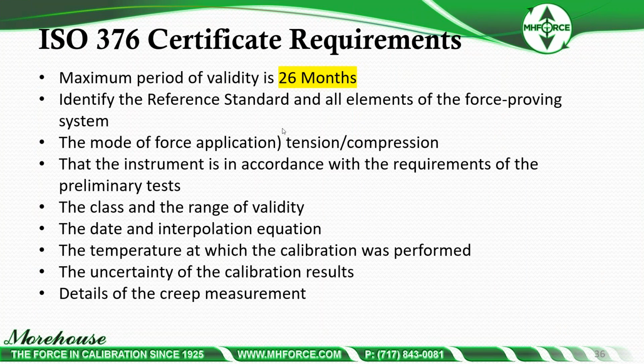I just showed you our typical certificate for ISO 376, the Morehouse certificate for ISO 376, but ISO 376 has additional requirements. Maximum period of validity is 26 months. Identify the reference standard in all elements of the force proving system. That's cables and everything else, top locks if they're included with serial numbers, everything. The mode of force application, tension, compression, that the instrument is in accordance with the requirements of preliminary test, the class and range of validity, the date and interpolation equation, which you saw that was a 3rd degree, the temperature at which the calibration was performed, the uncertainty of the calibration results, and then, if needed, the details of the creep measurement, which is when you did the creep test, what the results were.